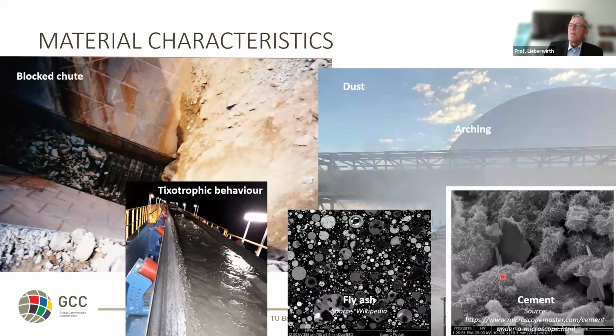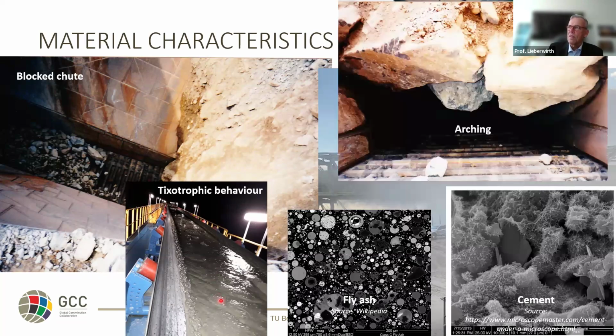This is the picture from the conveyor with this fluidized thixotropic material. Imagine this is material after a primary gyratory crusher, and this is what comes out there. You can imagine that on the first slope the material would flow back, and you get into problems with this system. And of course, the arching, most probably everybody has seen this already. When all of a sudden you don't get material out of your hopper anymore, the apron feeder is still operating and the hopper is full, but no material comes out. This was a nice situation of arching, which I photographed.